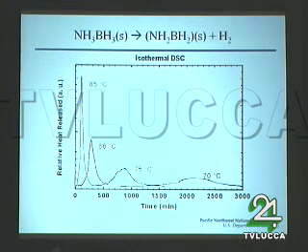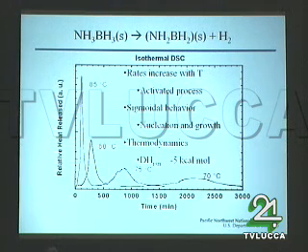When you have something like this, it's sigmoidal kinetics; it's not a simple first or second order process like you see in solution. And sigmoidal kinetics tell you, from people who are studying crystallization, that there are two steps to this. There's some sort of nucleation that happens to start the reaction, and then once that happens, it takes off and releases the hydrogen until about half of it's gone, and then it can't overlap anymore. So this rate increases with temperature. It's got this sigmoidal behavior, so it's indicative of some sort of nucleation and growth process.